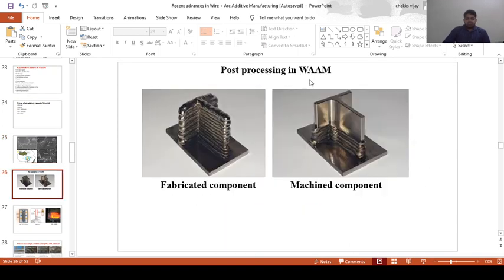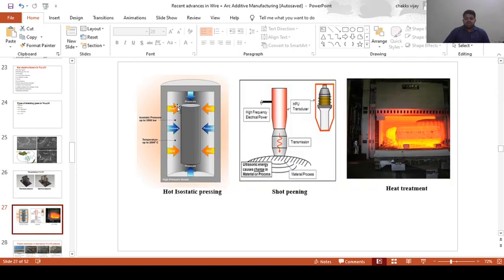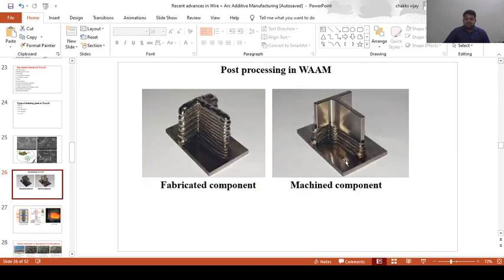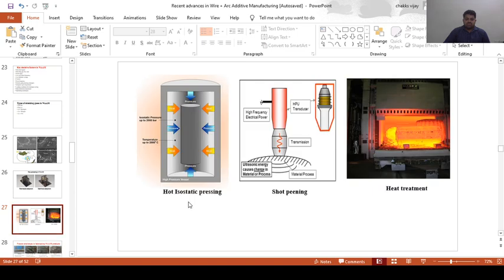So these are some of the post-processing techniques. Generally, after deposition we will be removing the material, so machining is one of the most important post-processing steps. Here we mostly never go for any kind of heat treatment, especially with wire arc components. However, if we go for very high heat input, there may be chances of residual stress formation, which may be due to the building of a very high thermal gradient.